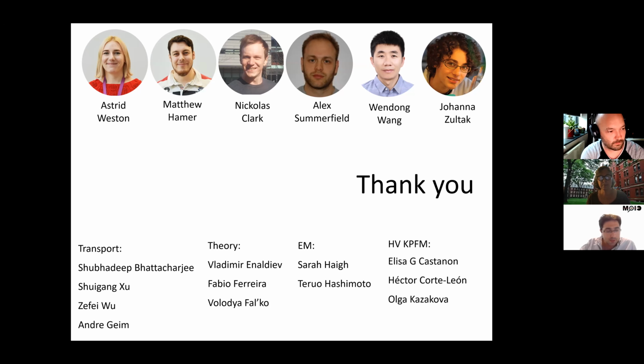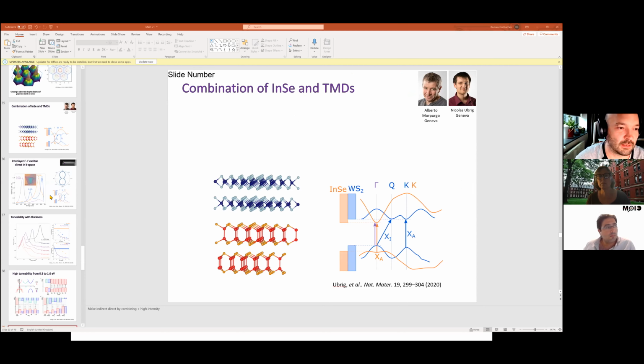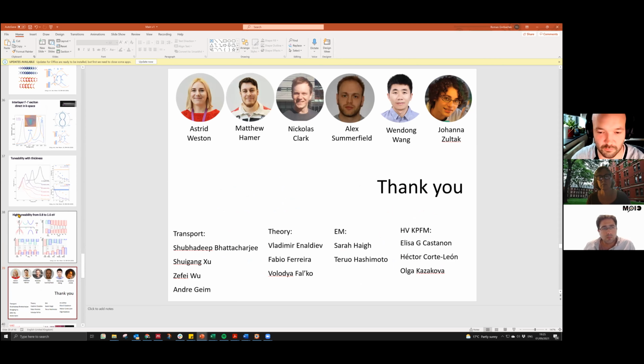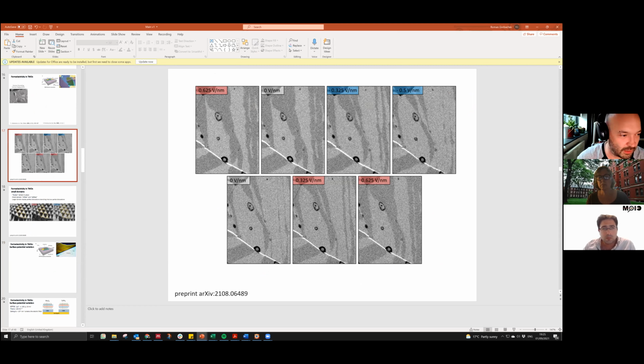The first question is a bit more practical. When you show the ferroelectricity in the TMDs, how thick is the BN in the SCM? How thick can the BN be to get these kinds of images when you encapsulate? So that's a good question. So yes, you need a very thin BN to observe this kind of images. We need less than 3 nanometers would be ideal.